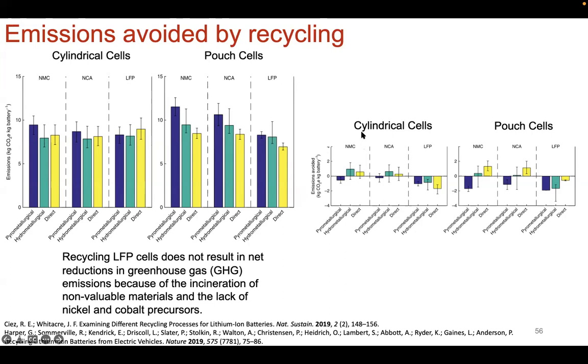And if you ask yourself, well, is there a gain? Do I reduce the amount of CO2 if I recycle LFP cells? What you see here is the emission avoided is actually negative. So why is that the case? That is because iron already avoids some of the CO2 emissions, the higher CO2 emissions relative to that of cobalt and nickel. So when you try to burn or recycle iron, the amount of energy, the amount of heat, the amount of electricity that you have to put in to burn all of this stuff, or acid leach or what have you, you actually don't avoid. So you're putting in so much energy to recycle lithium iron phosphate that you don't actually reduce the amount of CO2. You're actually contributing more CO2.